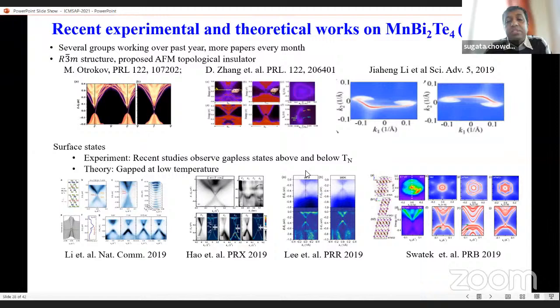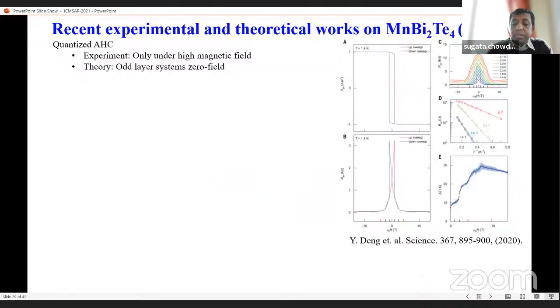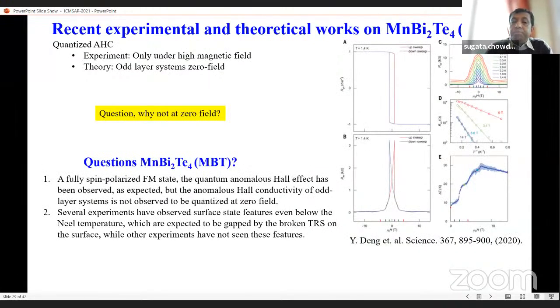The difference between experiment and theory is that the recent study observed a gapless state above and below the transition temperature, but theoretically it is predicted to be gapped at low temperature. The question is why there is a discrepancy between theory and experiment. And here they also find that at high magnetic field, not at zero magnetic field, the odd layer system shows the effect. The question is, why not at zero magnetic field?